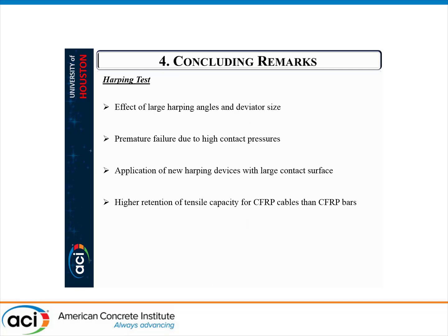And regarding the harping test, I talked about the effect of large harping angles and deviator sizes, and the premature failure due to high contact pressure. By using the new harping devices that we developed, it required more attention to be adopted by the industry and to be practical, which is still yet to achieve. And the application of new harping devices with large contact surface gave higher retention of tensile capacity for CFRP cable than CFRP bars in all cases.